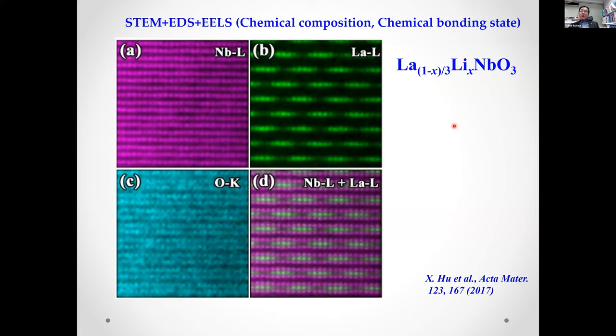You can even combine it with EDS and EELS. EDS is energy dispersive spectroscopy, and EELS is electron energy loss spectroscopy. You can obtain atomic resolution chemical mapping. This is an example obtained for ABF of LLNO. This is an EDS mapping of Nb, and this is a lanthanum L mapping. This is a composite chemical mapping, Nb plus lanthanum. You can clearly see the modulated structure. You can directly see such chemical composition distribution at atomic resolution. This is a very powerful technique. So we combine this with ABF imaging to characterize lithium ion related crystals.